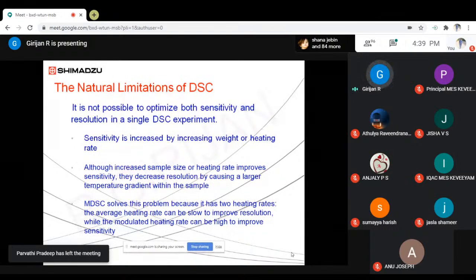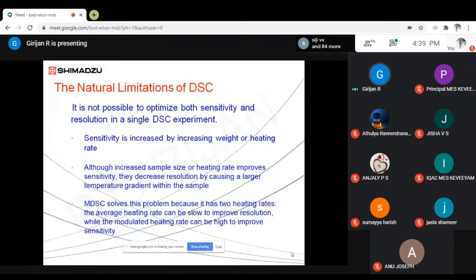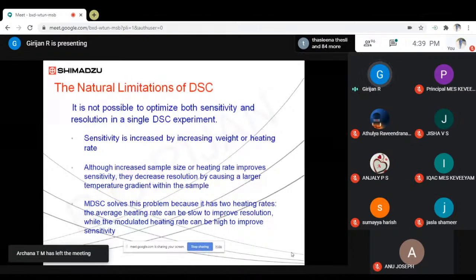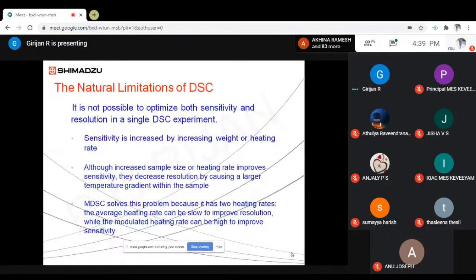But when you go for a modulated DSC system, it solves this problem because it has two heating rates. In the case of normal DSC, we have a single heating rate, a linear heating rate. But in the case of MDSC, we have two heating rates. One is an average heating rate, and the second is a modulated heating rate. Let's see what that modulated heating rate is. The average heating rate can be slow, so that improves resolution, and the modulated heating rate can be high to improve sensitivity. So that is how we increase the sensitivity and resolution at a time in a single experiment in MDSC, by using two different heating rates, one an average one and one a modulated one.